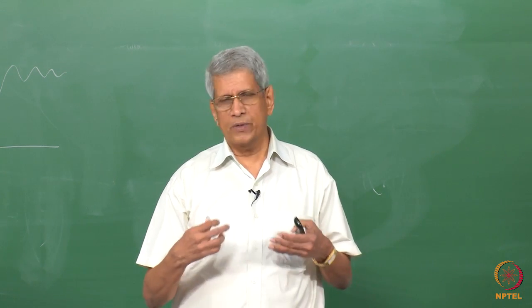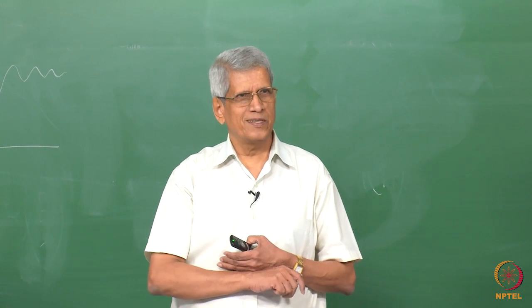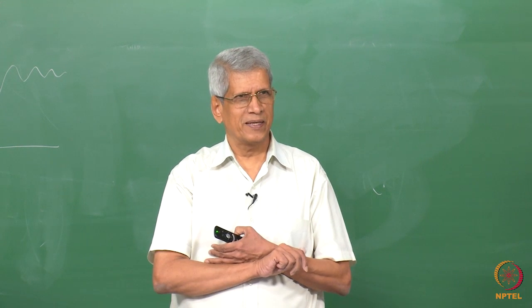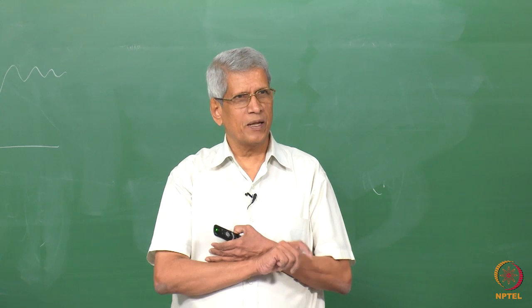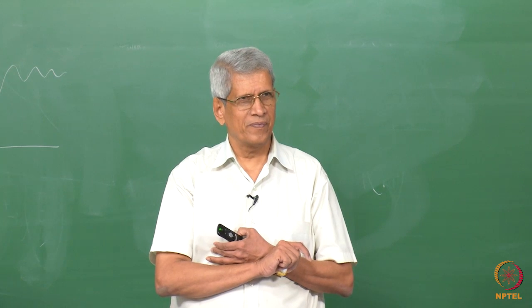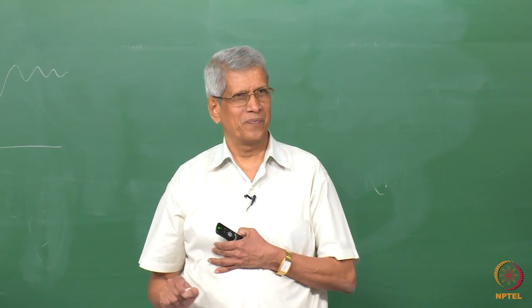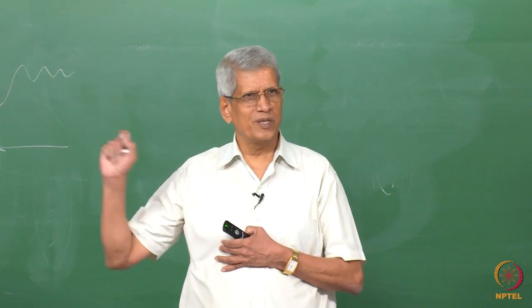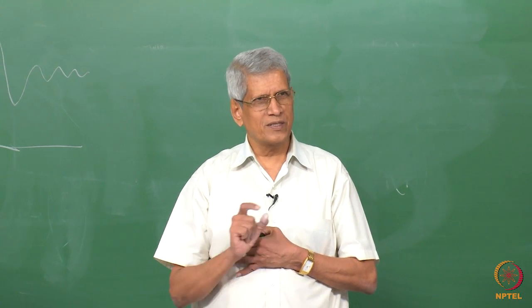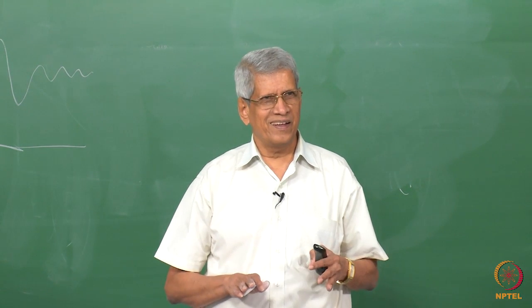This we are talking with respect to damping externally. Suppose in the material itself, there are some defects which are jumping from one position to the other. This jump itself, if it is random, can generate a preferential jump. It can also produce a damping in the material. This damping also will try to bring down the amplitude. So if we can measure how this damping is taking place, look at this plot, we can get some information about the migration energy. This is what is done in this experiment.